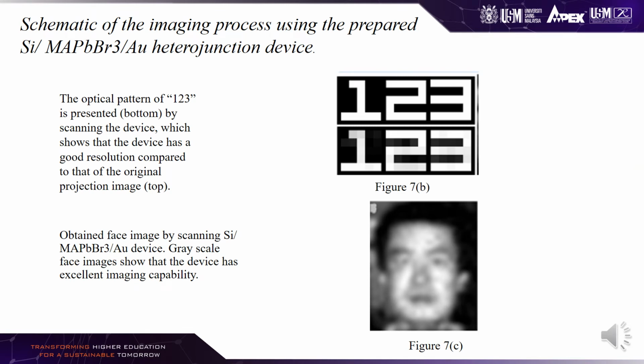Figure 7b shows the optical pattern of 1, 2, 3 presented at the bottom by scanning the device, which shows that the device has a good resolution compared to that of the original projection image at the top. Figure 7c shows the obtained face image by scanning silicon MAPbBr3 gold devices. The grayscale face image shows that the device has excellent imaging capability.